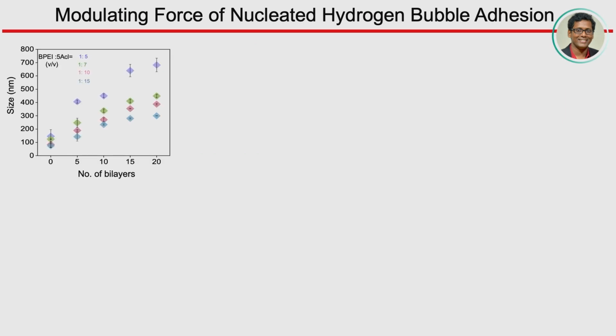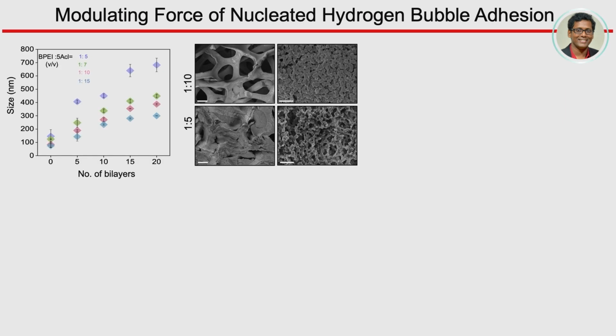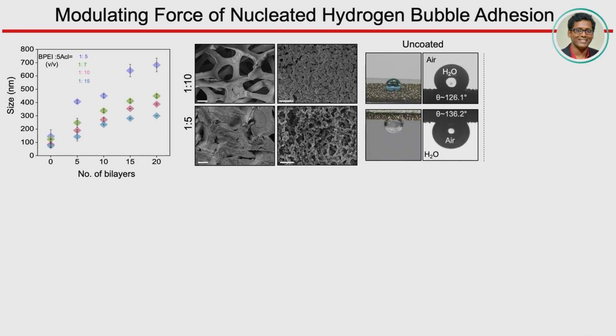You can see this is the kind of optimization conditions. I'm not going into details, it's already published. So what I can tell you in short is that the bilayer number and the dilution, or say the concentration, of this nanocomplex really play a role to get an optimum deposition without blocking the pores of the nickel foam, the inherent foam. And you see this association of the nanocomplex leaves behind some of the pores, which is important, right?